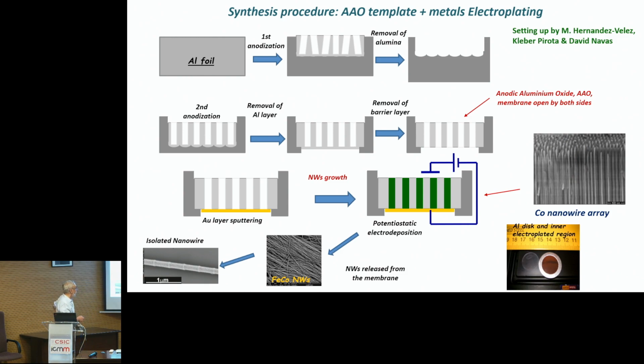So for that we have to remove chemically first the aluminum membrane and the gold nanolayer, and we have millions of these nanowires, and this is a very tedious work to separate them by centrifugal forces. So finally it is possible to get an isolated nanowire, and then we study the magnetic properties of individual nanowires.